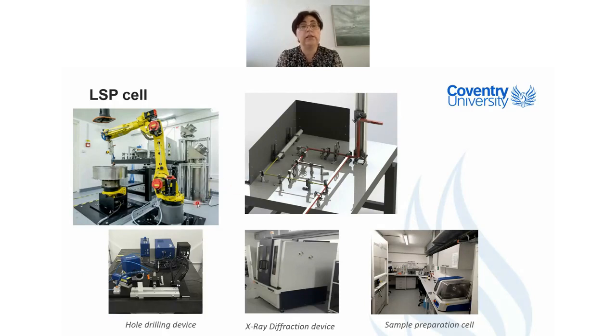For this laser, we designed something called a front end, because we would like to have a top hat beam with a square shape. And we also wanted a short temporal rise time, which means minimizing the time the laser needs to reach maximum energy. Also, we wanted 80% of the duration of the pulse to be at the maximum pulse energy.